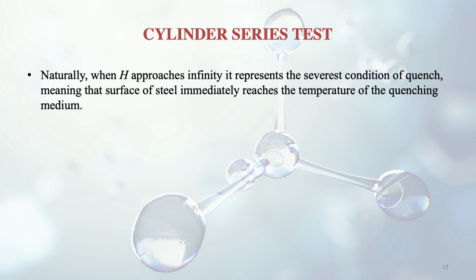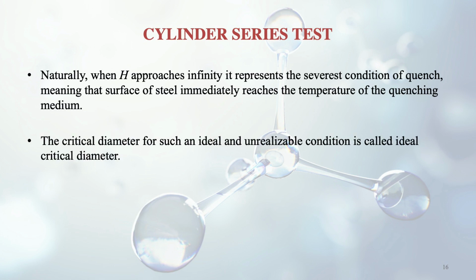So it is the ratio of these two things: the heat transfer coefficient between steel and fluid, and the thermal conductivity of steel. So when H approaches infinity, this value which we discussed just now represents the severest condition of quench, meaning as soon as the surface of steel is in contact with the quenching medium, it immediately will change into martensite, or it reaches the temperature of the quenching medium immediately. So the critical diameter for such an ideal and unrealizable condition is called the ideal critical diameter.